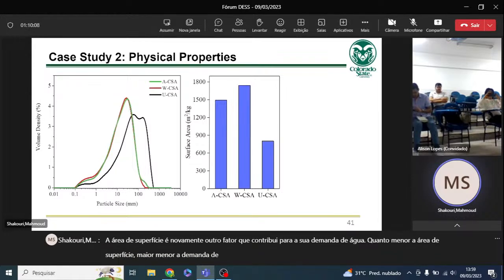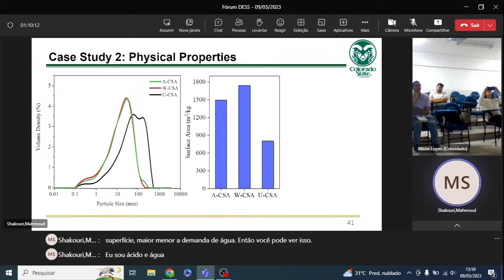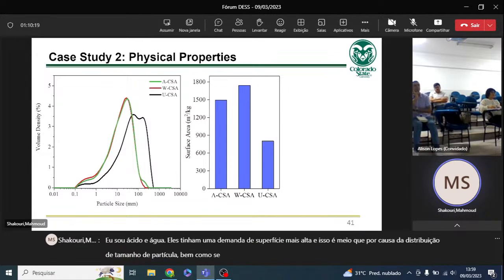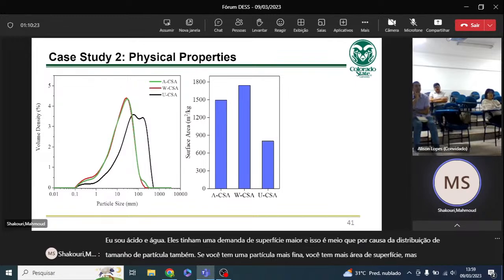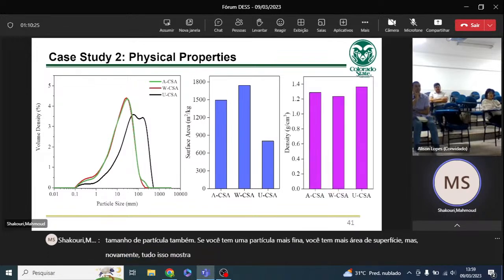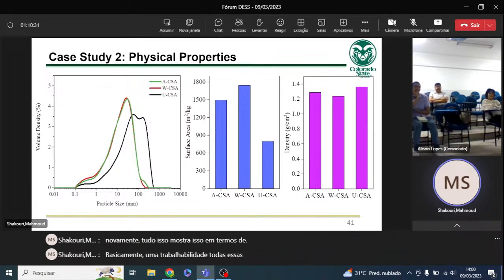So you can see that A-CSA and W-CSA had a higher surface demand, and this is because of the particle size distribution as well. If you have a finer particle, you have more surface area. But again, these all show that, in terms of workability, all of these ashes reduce your workability.